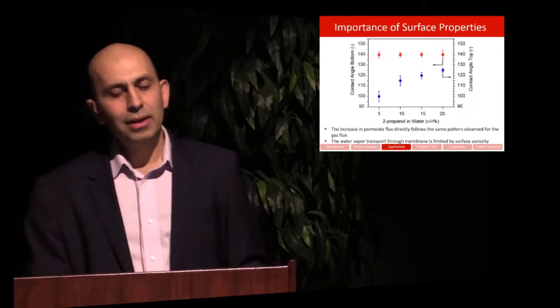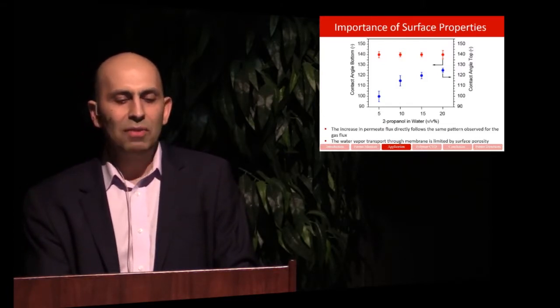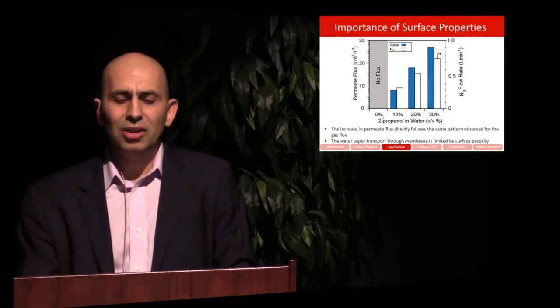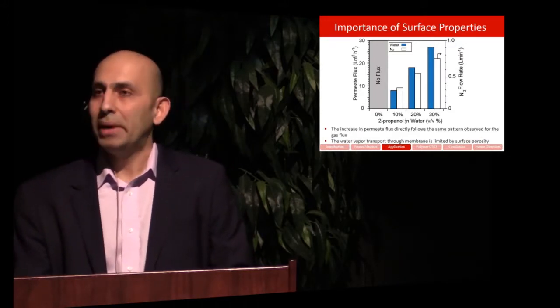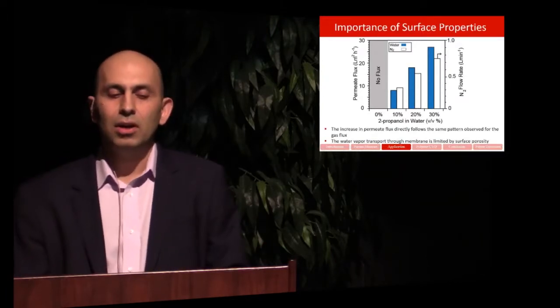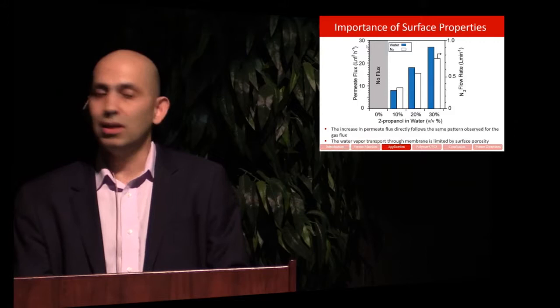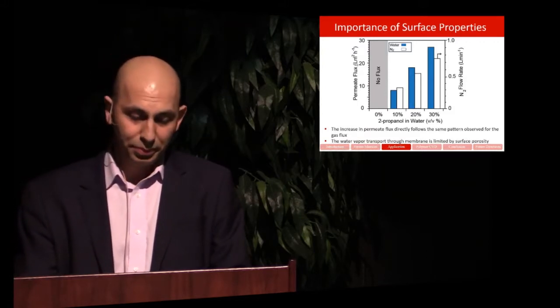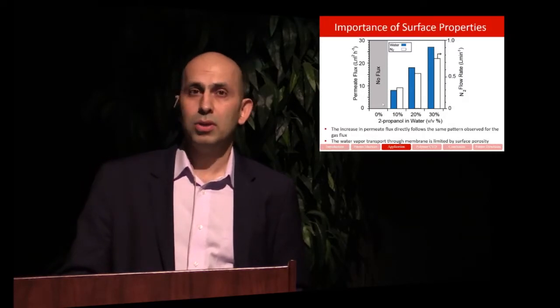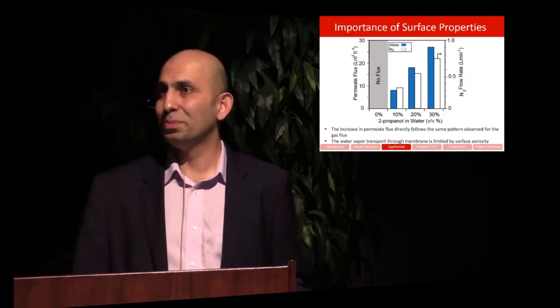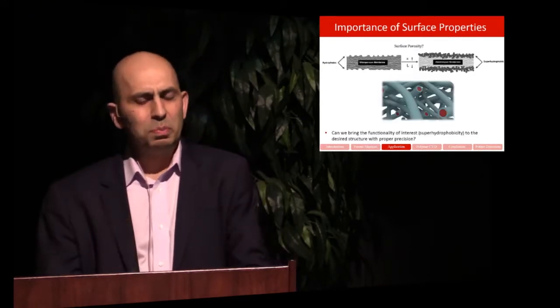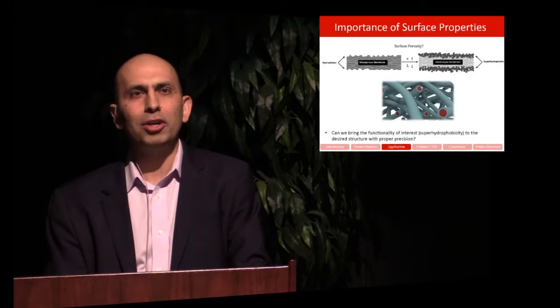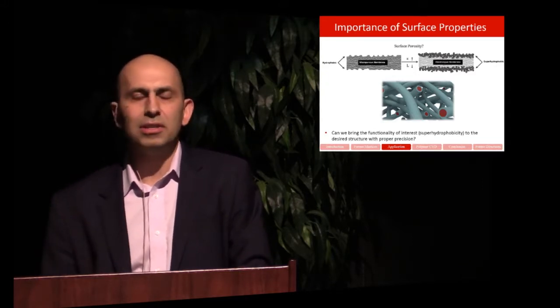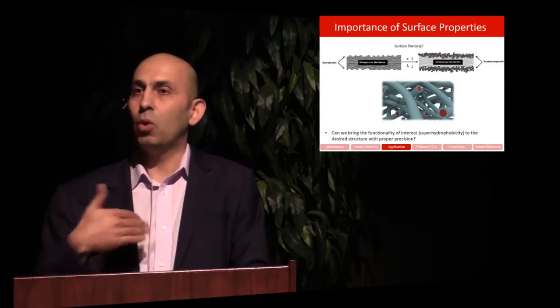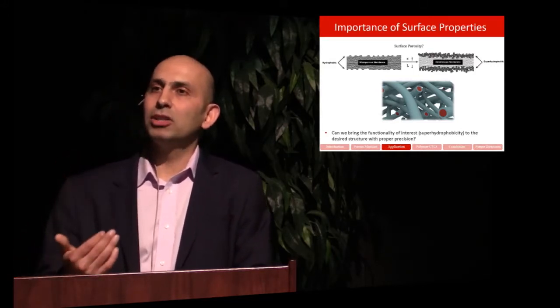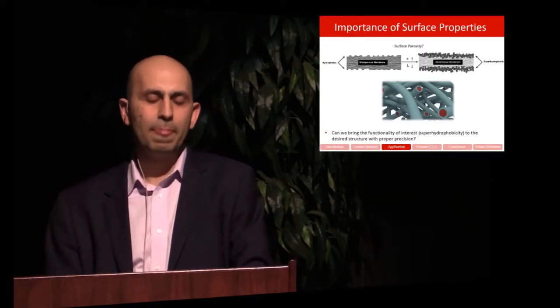So we started looking at the different properties of this membrane, and we looked at the flux. What we learned was that the higher the 2-propanol in our coagulation bath, meaning the higher the open surface area, we could get higher flux. And we could achieve about 30 LMH of flux for this membrane. So if that's true, the highest possible opening means the best membrane possible. So can we do that? Do we have the required toolbox to create a highly open surface and adjust the surface property so we can repel water, let the vapor go through, and enhance the flux by adjusting the structural parameters of this design?